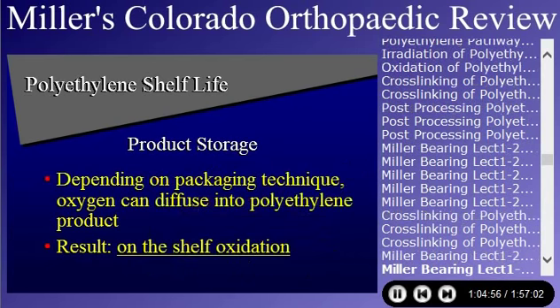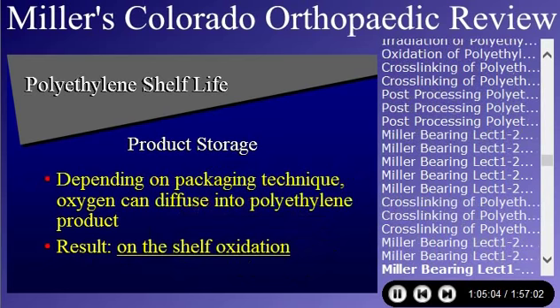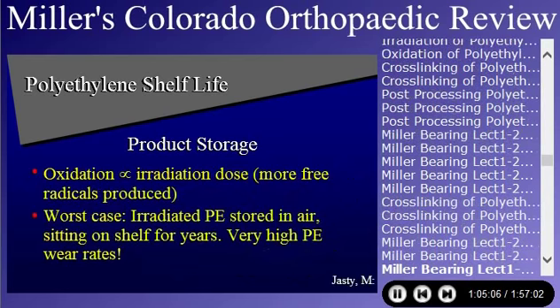And so depending on the packaging technique, oxygen can diffuse back into the polyethylene product, and the result is you get on-the-shelf oxidation. And the problem is that oxidation is directly related to the irradiation dose. So if you do high-dose irradiation and then you store it for a long time, you're going to get more oxidation on the shelf because you have more free radicals in there. The worst case is irradiated polyethylene stored in air. And that's what happened in the earlier ones.